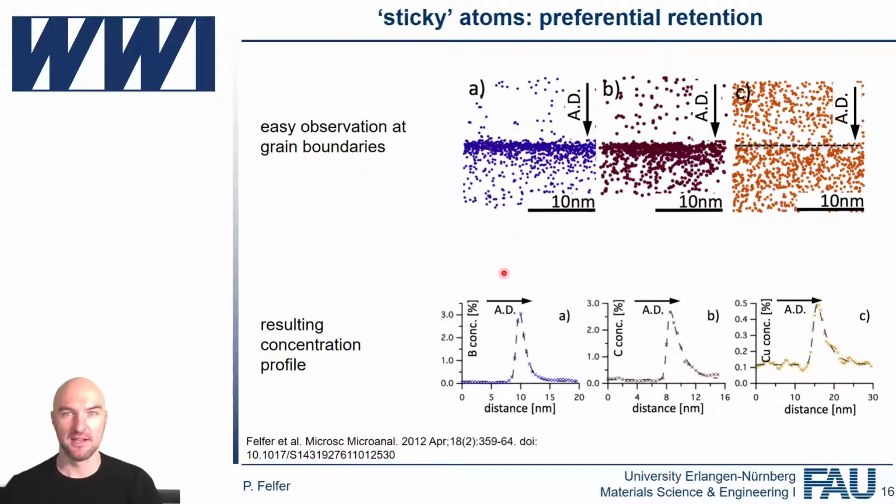This effect is breaking neighborhood relationships, because one of the boron atoms that came off here is probably 2 or 3 nanometers away from its original neighbor in the reconstruction, or when the field evaporates, it's already a couple of nanometers away from its original neighbor here. Obviously, the probability for it to stick around for that long is relatively low, but it's not zero. Again, this demands some mobility of the atoms. So if you're looking at atoms that are locally very strongly bound, then this effect plays less of a role.